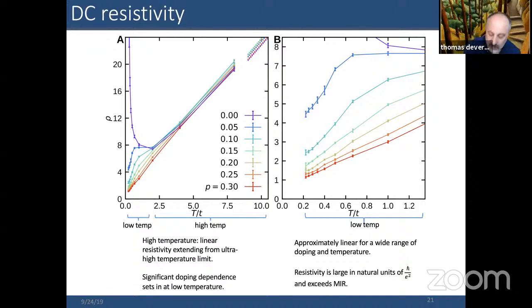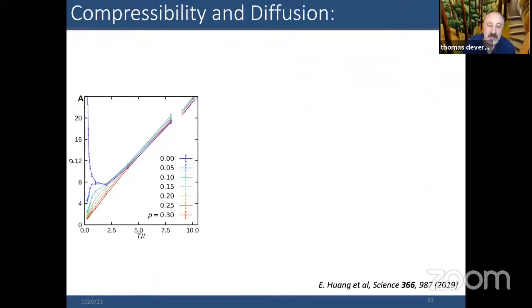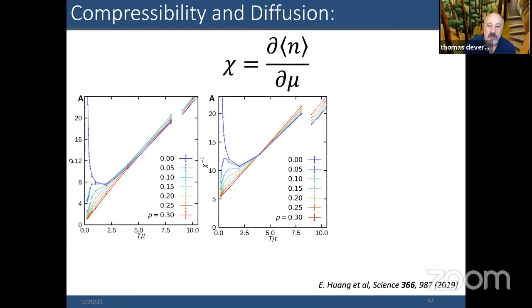As a typical signature of the fact that these are extremely bad metals. And so you can analyze the data by comparing the resistivity to the compressibility, for which no analytic continuation is needed, or plotting one over the compressibility. Again, it's not a surprise that it's linear at high temperatures, but it persists and comes down linearly with temperature, but it comes to a finite value as T goes to zero.